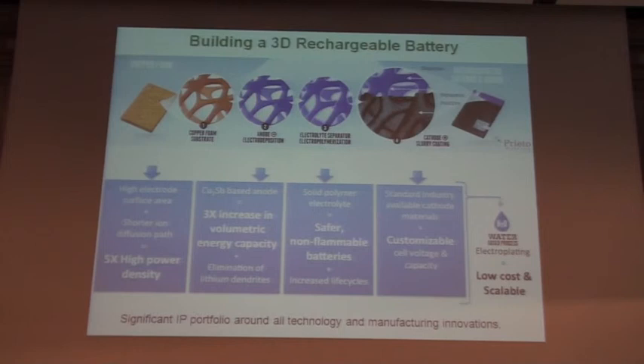So we use this as our working electrode, then we directly electroplate our anode material. In this case, we had to choose something that could be directly electroplated, so we can't use graphite, which is the normal anode material. And I will tell you a little bit more about this compound in a moment. But what you need to get away from it is that it has a 3 times higher volumetric energy capacity than graphite. And more importantly, chemically, it's quite a bit safer than graphite. So it eliminates the potential of plating lithium metal, which is one of the major causes of shorts in current lithium-ion batteries. The compound that we use, copper antimonide, is also a very good metal.